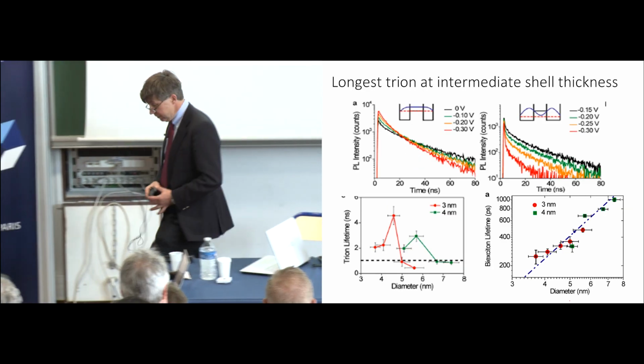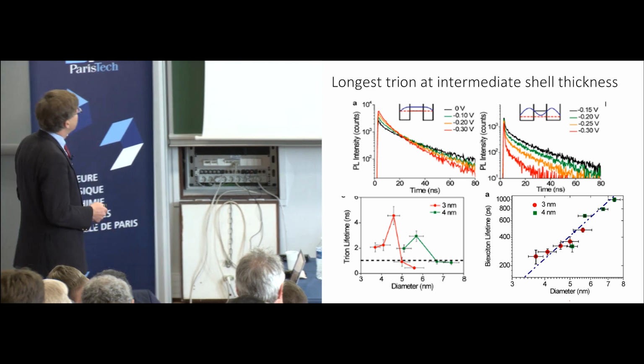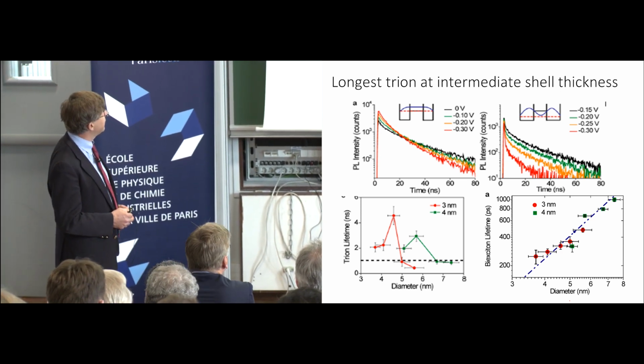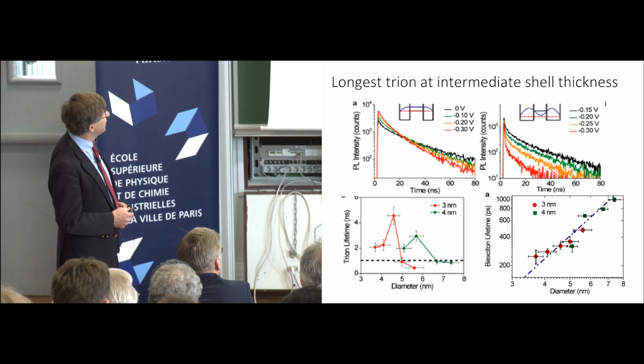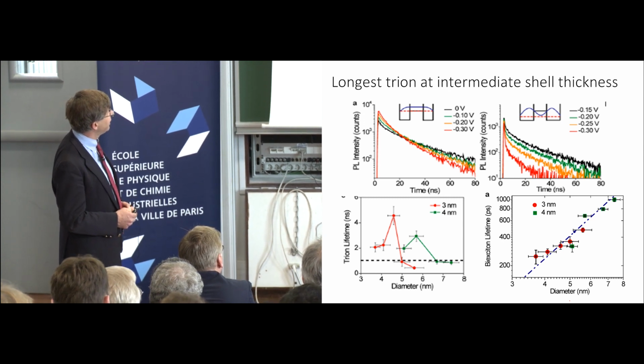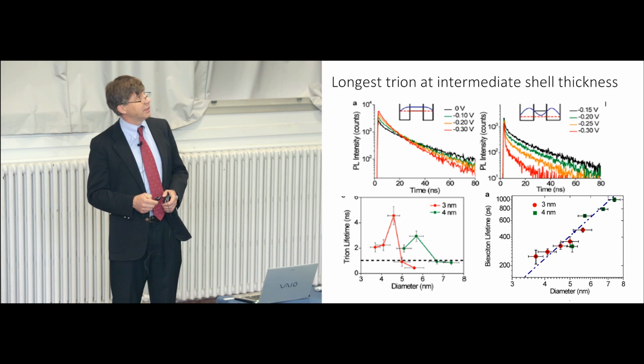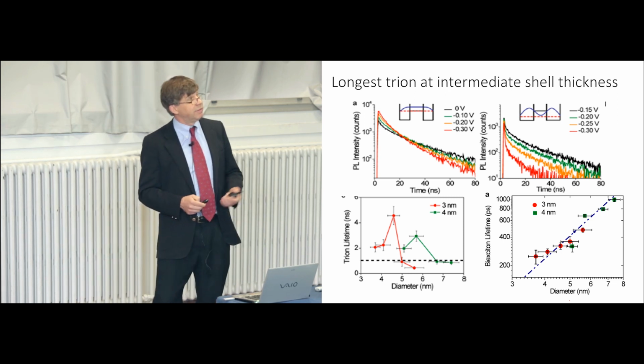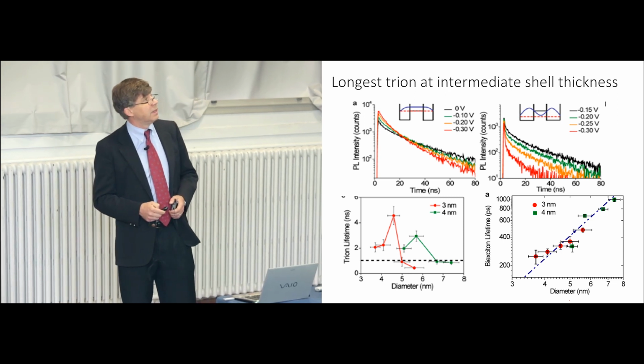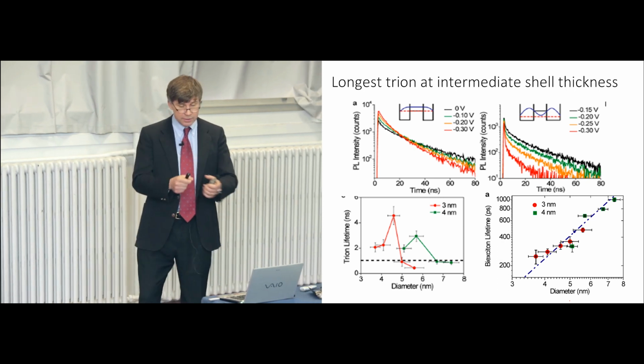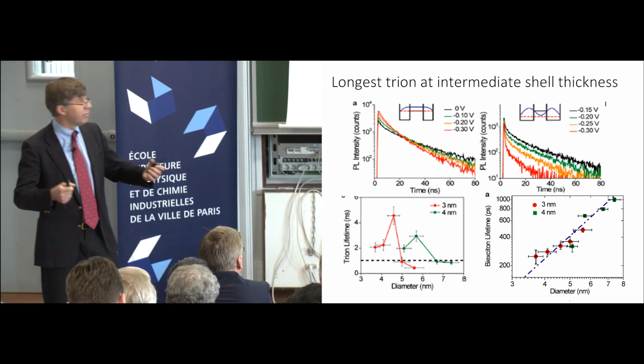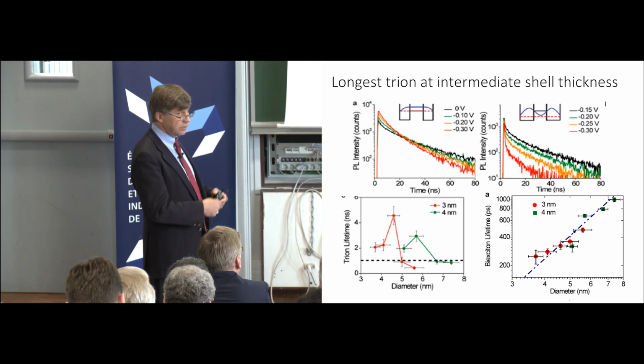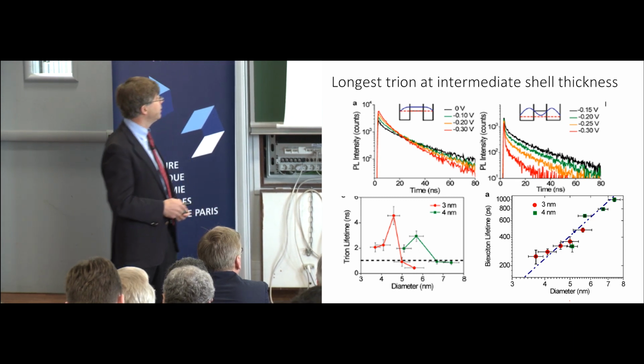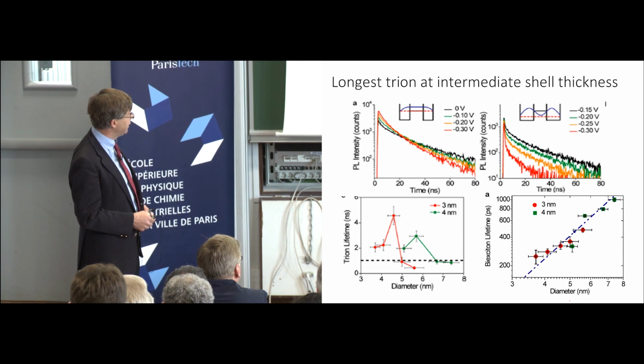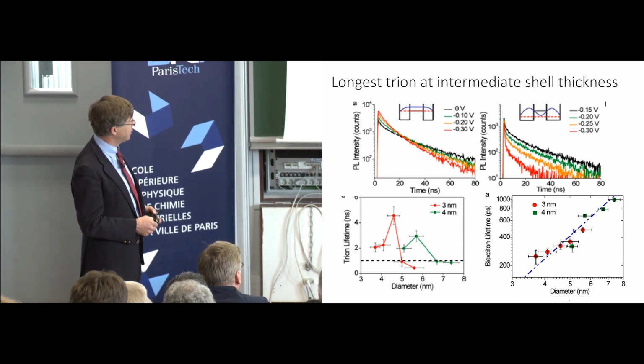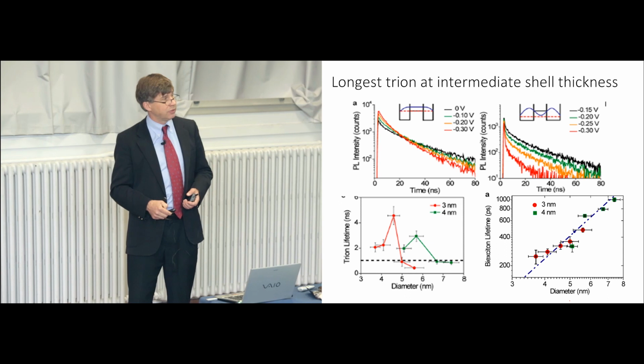And what we found, and that was very surprising, and that's fairly recent work, just last year, was that the trion lifetime, or the charged dot lifetime, gets faster, of course, than the neutral dot, but it's non-monotonous. Extending the range between the electron and the hole does not monotonously increase the trion lifetime. There seems to be a peak. So the trion lifetime starts short, gets longest at some intermediate shell thickness, and gets short again.